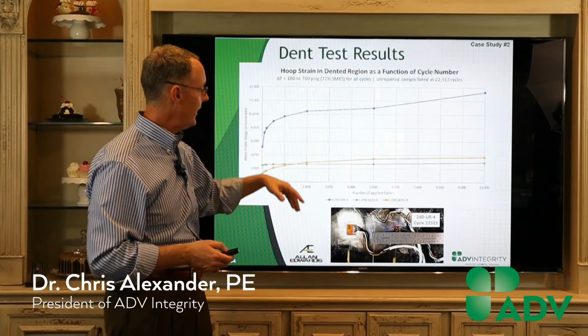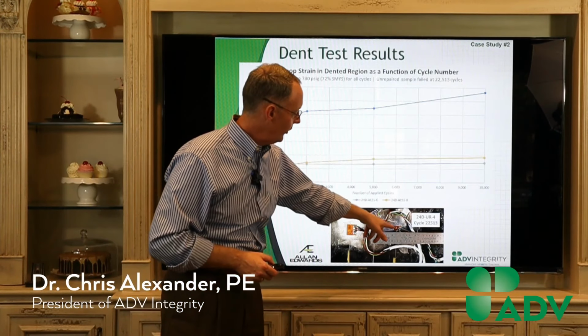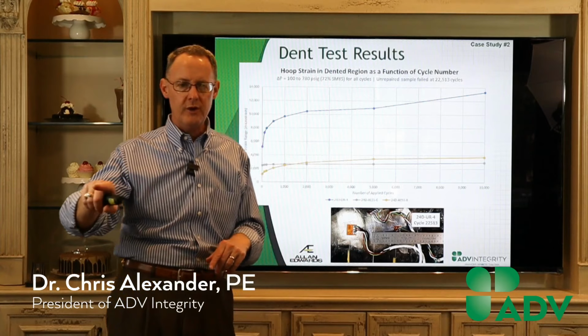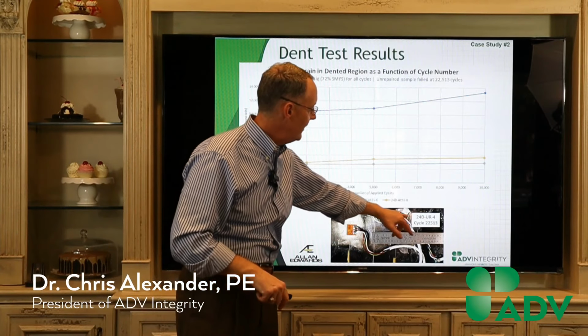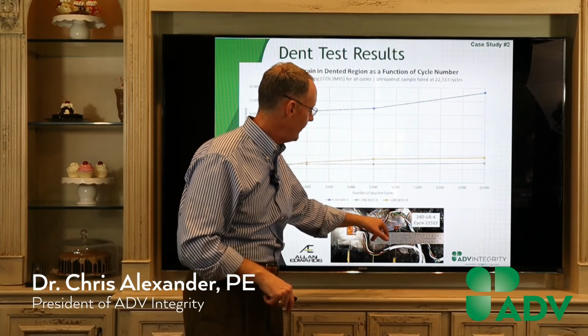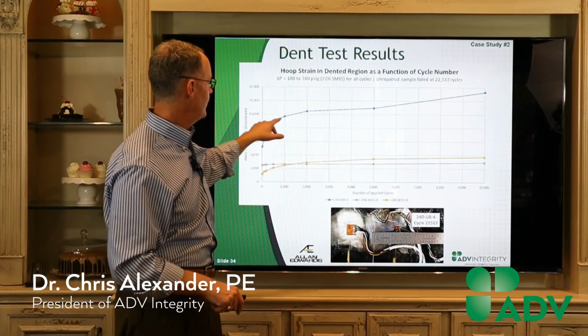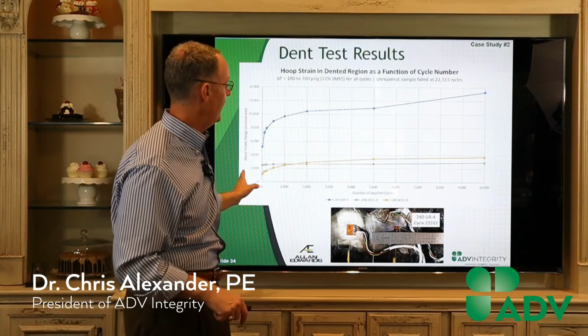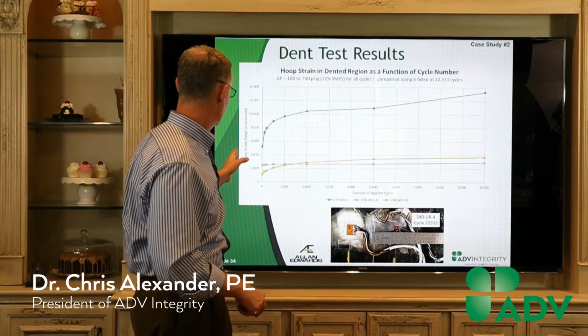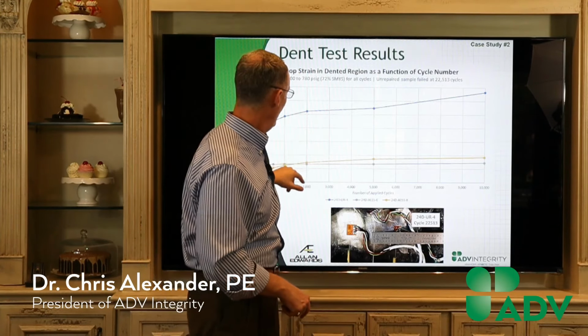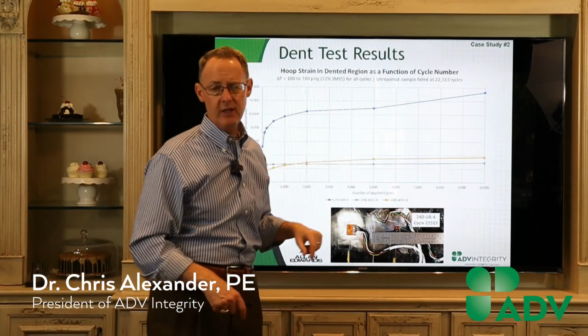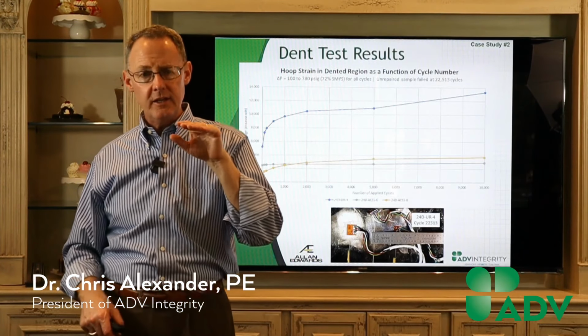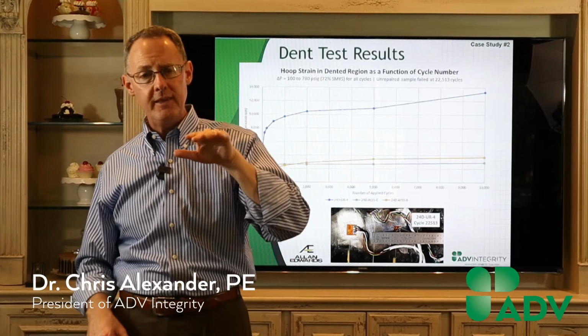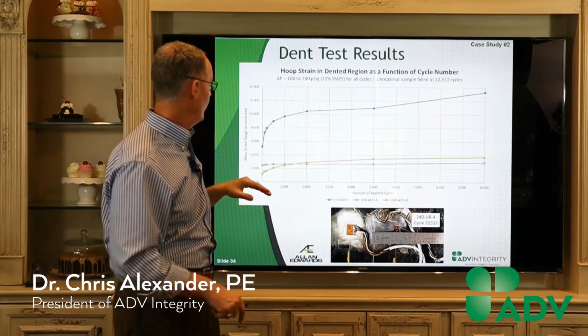And these are some strain gauge results. As I alluded to earlier, anytime you get a crack that runs underneath the strain gauge, this is the dent, it failed in about 22,000 cycles. That fatigue crack ran right through the strain gauge. So what that shows us is, as I'm increasing my number of cycles, the strain in the dent's going up. What I like in this graph, though, when you look at the yellow and the gray, is that the steel sleeve is keeping that strain consistent and relatively low.